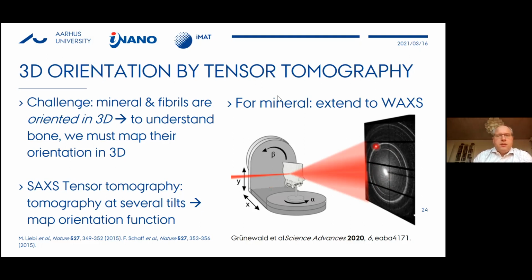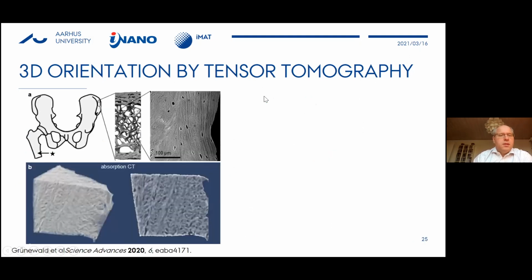So we looked at data from a human. This is from the iliac crest, where we extracted a part of the iliac crest containing lamellar bone. And in the bottom, you can see the sample that we were working on. There you can see the mineralized collagen fibrils themselves. You can see here that there's sort of a co-orientation this way and a different orientation in between. So these are individual bone lamellae we could trace along the specimen.